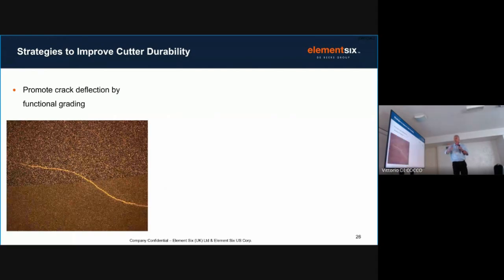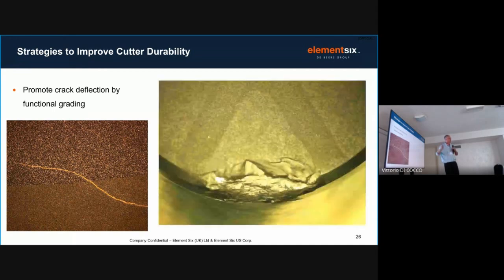Functional grading. Can we take different types of PCD? When I say different types, I'm talking about different volume content. So remember the 95.5, maybe 96.4, 93.7 will have different cobalt content, therefore different thermoelastic properties. Therefore, we will get crack deflection through the approach of functional grading. These sort of pictures, we make them in the lab and they look great and they look good in a paper and they look good in a patent, but do they change the overall performance of the cutter? Still struggling with this. Looks good on paper, hard to make it count in real life.